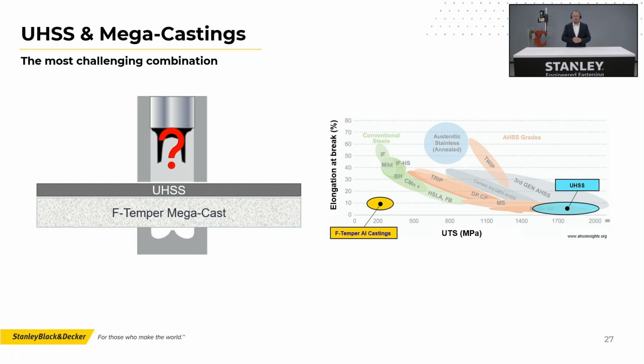Here you can see what I'm talking about. On the right side, again, it's the elongation at break to ultimate tensile strength graph. The yellow circle that you can see, that's the F-temper castings. They are around there. And the blue one on the right side, that's the ultra high strength steel up to 2000 megapascal. So in this case, you want to join these most critical materials together, one on the left side and one on the right side. It doesn't get any more challenging than that.